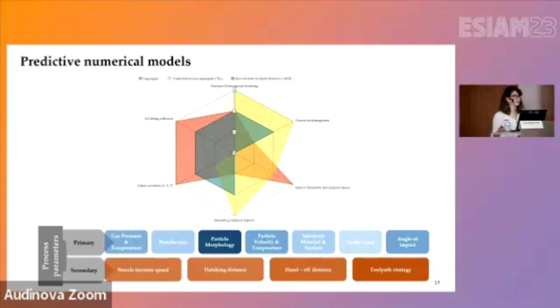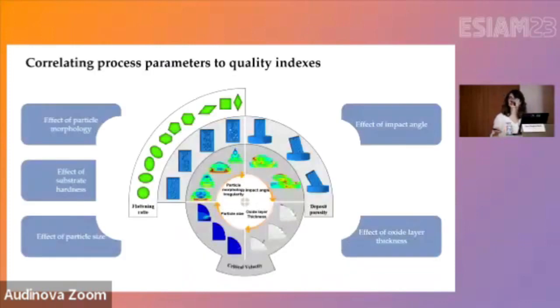which include gas pressure and temperature, the powder parameters, that is size of the powder, size of the particle, morphology of the particle, velocity and the angle of impact, and then the secondary parameters that are more related to the movement of the nozzle that is moving the head and the gun of the spraying, so traverse speed, hatching distance, standoff distance, and so on. I'm not going into the details, but just showing you a framework about a numerical model that we have developed. For example, in this case, for checking the effect of the particle characteristics on different quality indexes of the deposit.